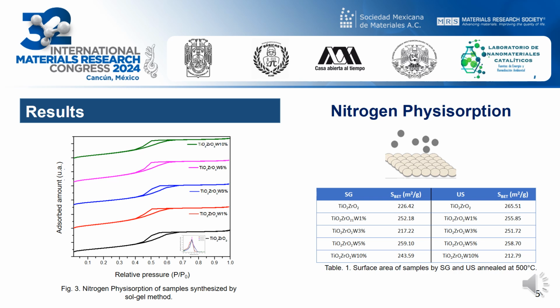The sol-gel method shows higher pore volume values with a maximum of 0.31 cubic centimeters per gram at 5% tungsten content and a minimum of 0.28 cubic centimeters per gram at 10% tungsten, while the sonochemical method exhibits lower pore volume values with a maximum of 0.21 cubic centimeters per gram and a minimum of 0.12 cubic centimeters per gram. At last, it was detected that the pore diameter for the sonochemical method is more uniform than for sol-gel materials.